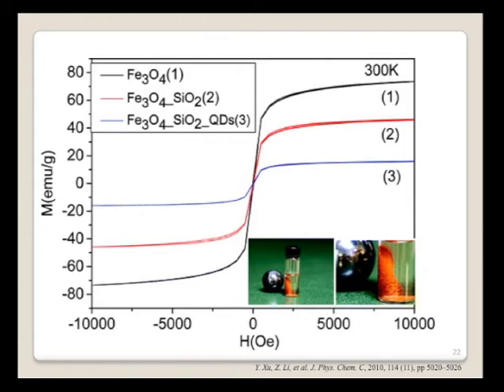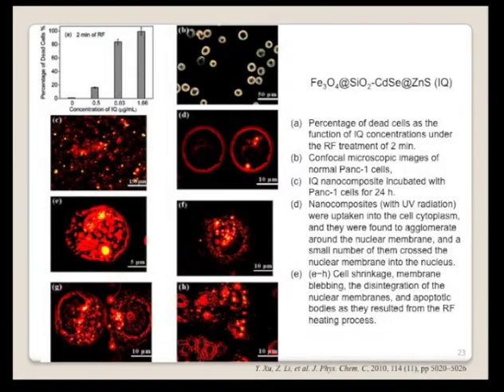Okay. So to further verify the magnetic property of this composite we just made, we can use a magnet. Put it on the side of this bottle of solution. Usually it's a brownish solution, very uniform. But when you put a magnet, you can separate the nanocomposite from the chloroform solution. Right? So the nanocomposite we synthesized is magnetic.